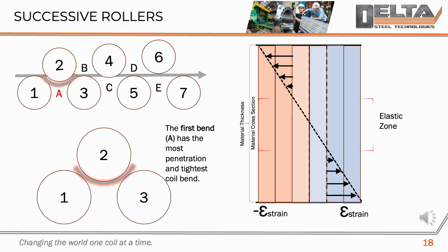Over the next 5 slides, we'll follow the progression of a steel sheet through a 7-roll leveler, focusing on one bend at a time. Let's start with the first bend, marked in red with the letter A on our diagram. This initial bend has the deepest penetration and tightest curve of any point in the process. Here, we achieve maximum deformation as the material bends around the roll, with the outer fibers experiencing both compression and elongation, with an elastic zone in the center.